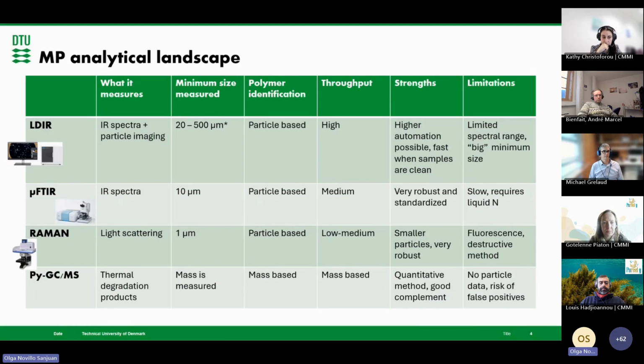The Raman is a very nice technique as well, and it goes down to smaller particles, but it requires a bit more training, I would say, or experience. If you work with environmental samples, you would probably face the issue of having a lot of fluorescence in your spectra. For those of you who are not familiar, although we will introduce this matter better after, it can mask your actual material. So it's very difficult to identify sometimes, depending on the sample.